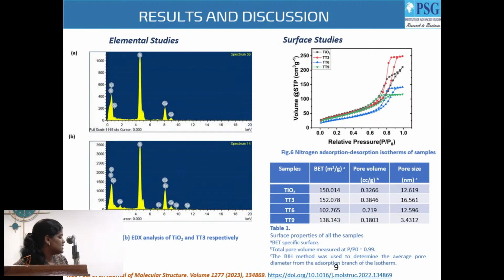These are the EDS analyses of TiO2 and TT3. In the TT3 compound, tantalum is present in a very minute percentage, since we have added only 3 weight percentage of tantalum. Then we moved on to the surface studies, in which we observed tantalum with 3 weight percentage showing the highest surface area of 152 meter square per gram, which is a good surface area, suitable for photocatalytic applications.